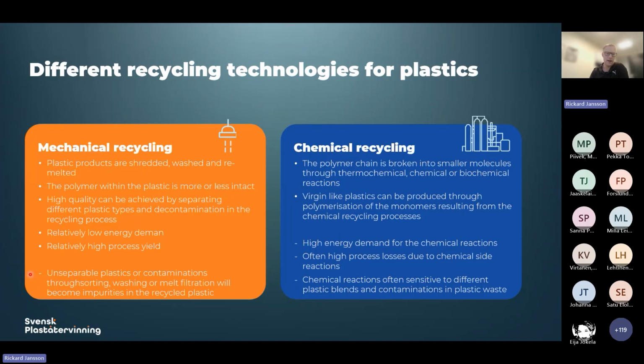So anything that you haven't efficiently washed out of the material, potentially chemical products and such, would remain within the material. And you also have the additives that were potentially added to different plastics in the first use phase. Those additives will typically also remain in the recycled plastic. So if you don't have very good traceability of what kind of material goes into the recycling process, you have a risk of potentially hazardous additives within the material as well.